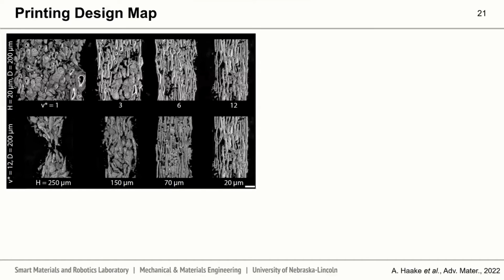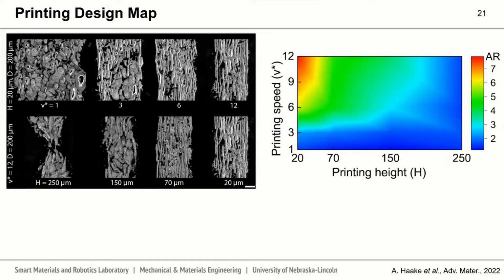From 16 independent experiments of velocity and height, we formulated a design map where generally, as print speed on the y-axis is increased and printing height on the x-axis is decreased, we see an increase in the aspect ratio of these liquid metal fillers, shown as a color map here.